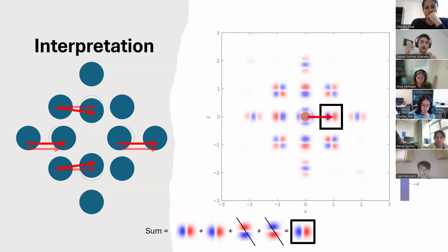Okay, so you can imagine that for a real crystal, this would get very complicated very quickly because, in this picture, we have one atom and another atom, and they're the same atom, and they're a unit cell away. I guess that's always true for real materials. But there's only one site, right? But you could have equivalently a second site with a different atom, and then it also has a neighbor that's 1 unit cell away, and it might have different motion or different correlations. So a lot of things are going to overlap here, and it's hard to interpret, as we'll see in a second. So don't worry about fully understanding every possible type of correlation, but we do want to get a basic idea of what we're looking at in terms of these dipole looking things.